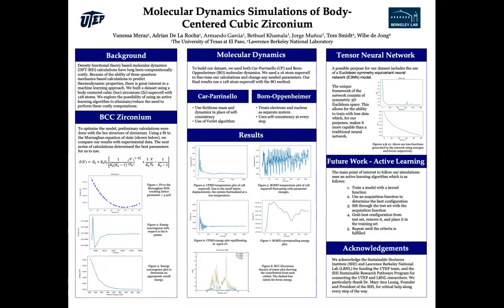So as a starting point, we were able to verify and compare our experimental values to our computations. The first set of calculations were done with different lattice parameters that were then fit into the Murnaghan equation of state. The result it gave us was a lattice parameter of 3.52 angstroms, which has a difference of 3% in comparison to the experimental data.